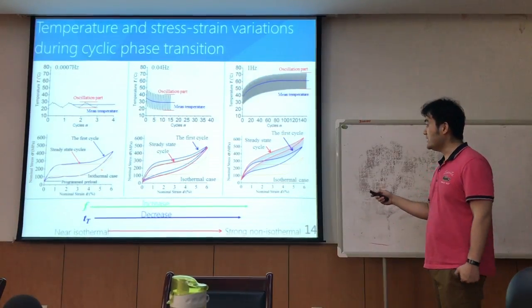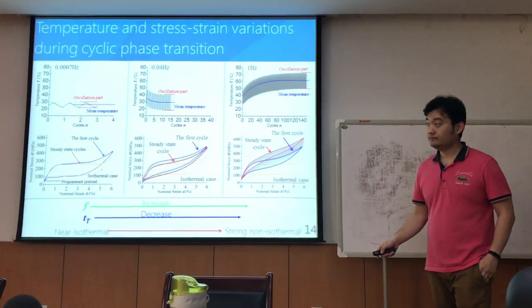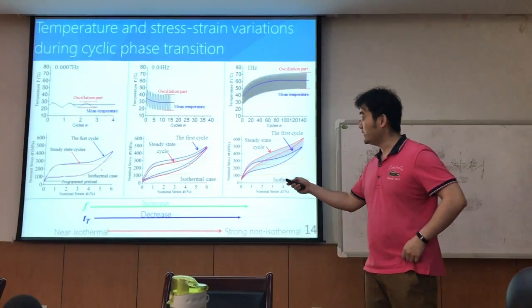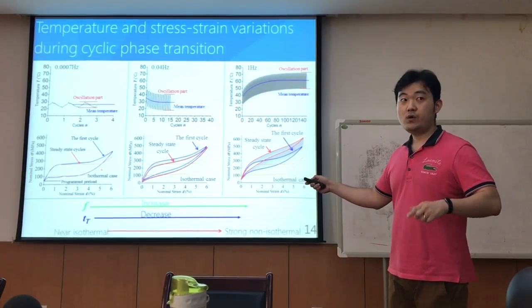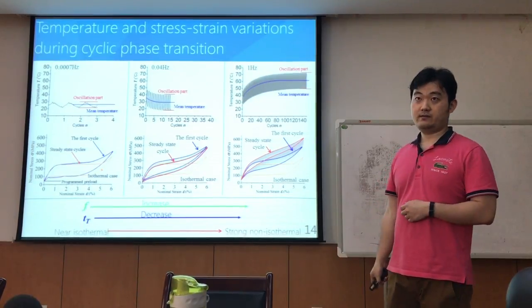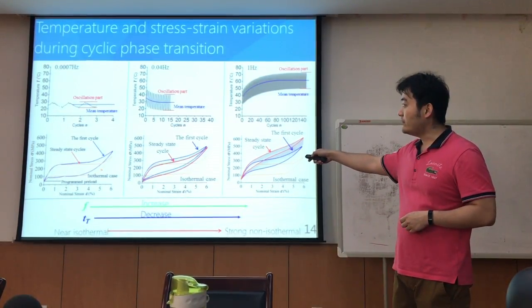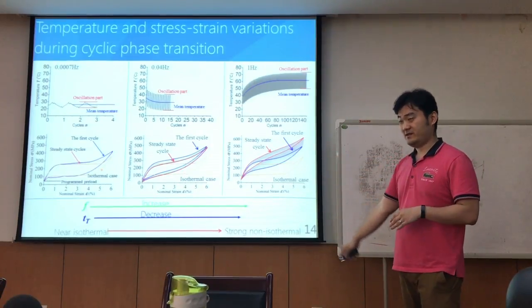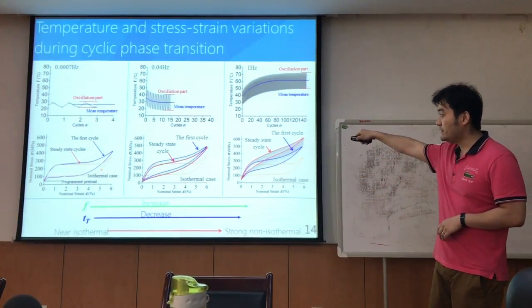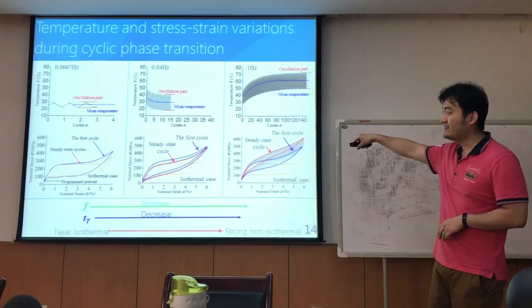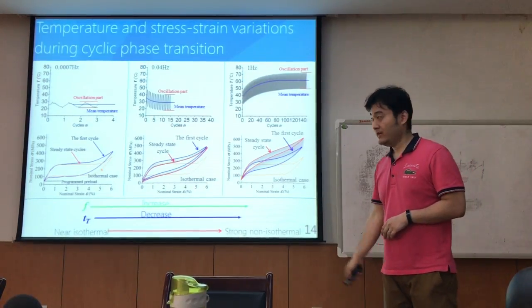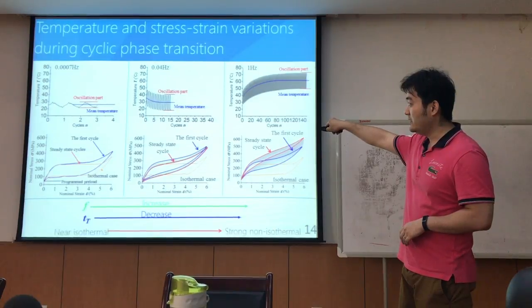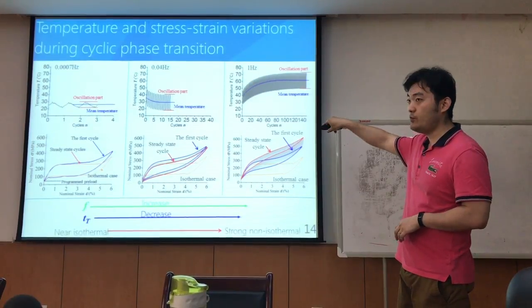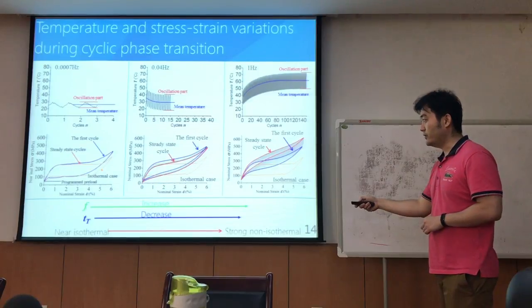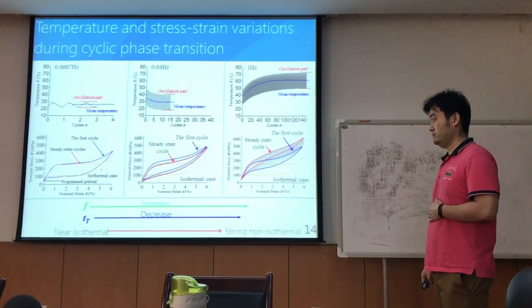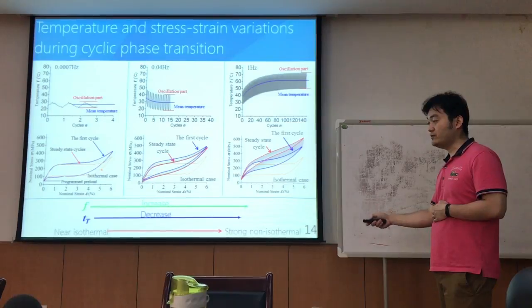Here I show three typical experimental results. We can see that under very low frequency cyclic loading, the temperature variation is not that significant. The temperature variation amplitude is less than 10 degrees Celsius, and it looks almost the same for each cycle. Of course, the stress strain curves too. They are very close to the isothermal case.